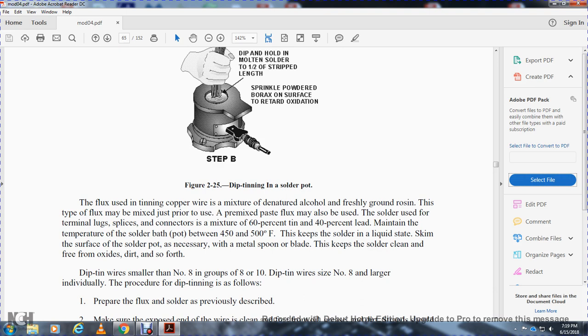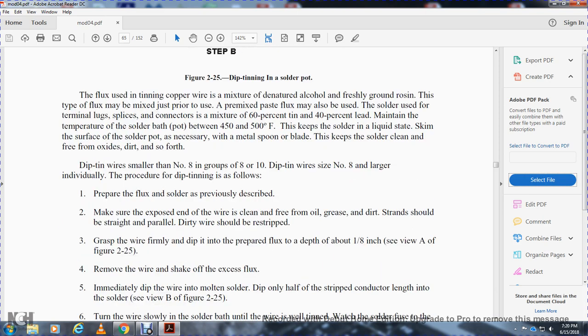The solder used for terminal lugs and connectors is a mixture of 60% tin, 40% lead. Maintain the temperature of the solder bath pot between 450 and 500 degrees to keep the solder in a liquid state. Skim the surface of the solder pot as necessary with a metal spoon or blade. This keeps the solder clean and free from oxides, dirt and so forth.